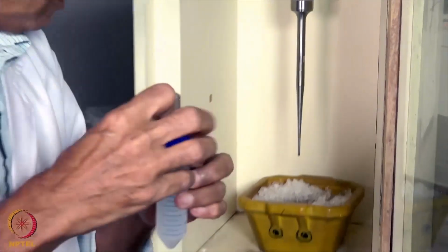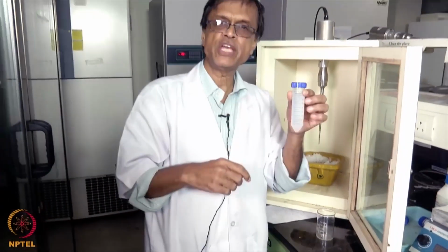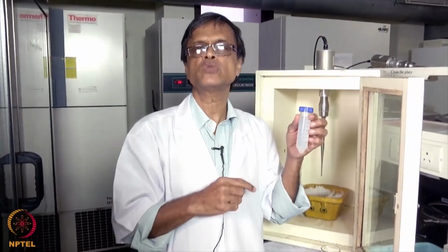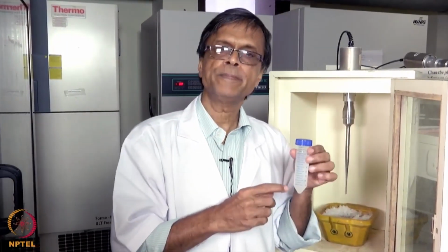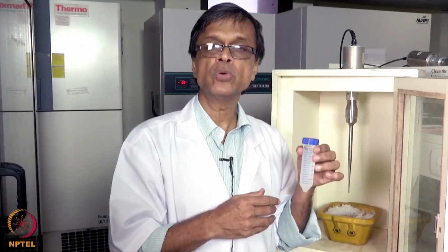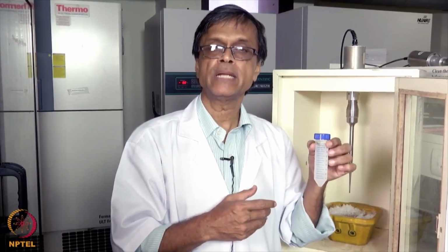This goes into a centrifuge, and centrifugation is done for 10 minutes at 10,000 rpm, and later on to a lyophilizer where moisture is removed and we get a very fine product at minus 60 degrees centigrade overnight.